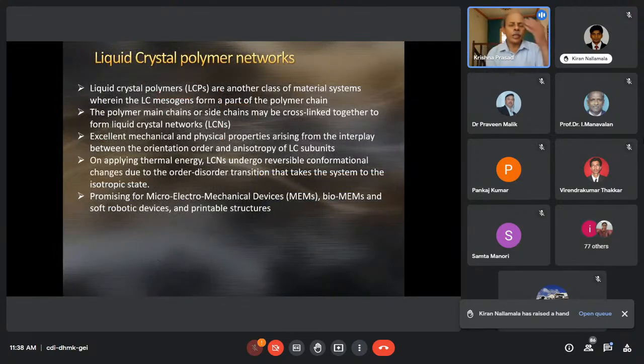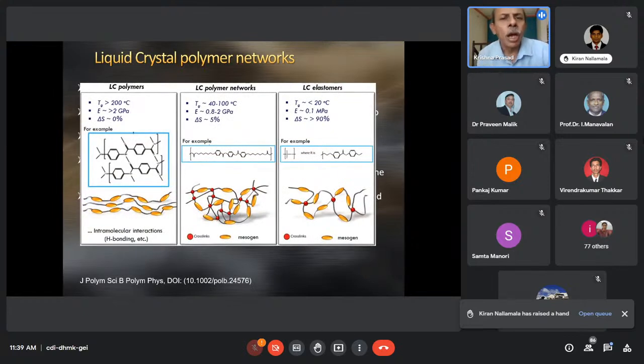When Divya wanted to start on using liquid crystal systems, the polymeric systems that we are talking about are the same base systems that we have with monomeric liquid crystals, except that now the mesogens could be forming a part of the polymer chain itself. And if you have cross linkers in these systems, they will give rise to liquid crystal networks, which, depending on the concentration or the architecture, you can end up with either simple LC polymer networks, which will have a high Tg, the glass transition temperature, with an associated high elastic rigidity, or you can also create elastomers whose Tg is very low and whose rigidity is also very low.